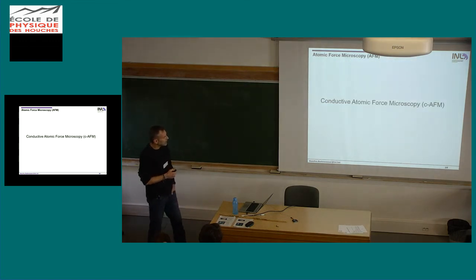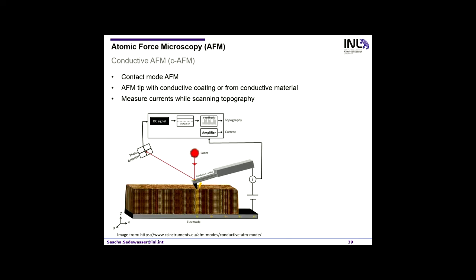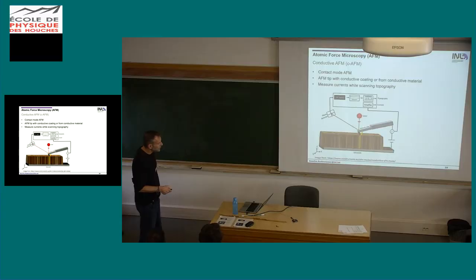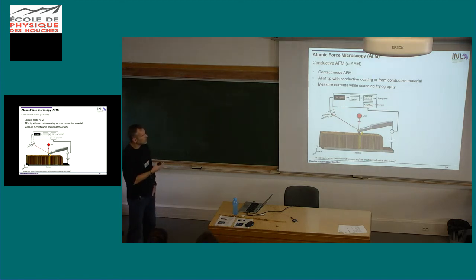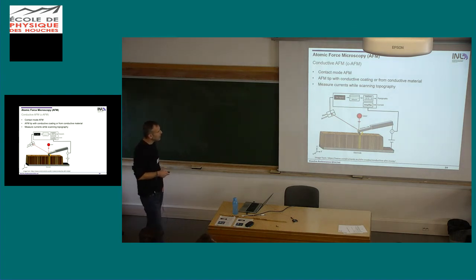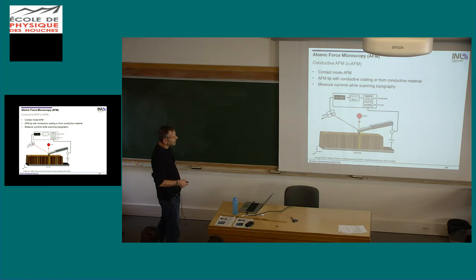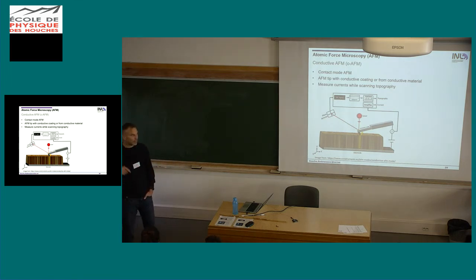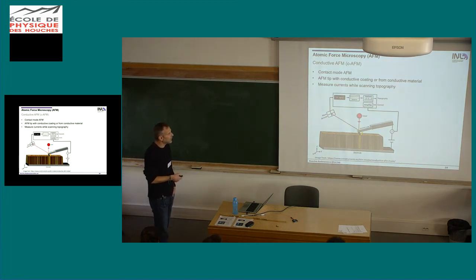The next method is conductive atomic force microscopy. Here what you do is you use a conductive tip and you go again into contact mode, but this time you don't want an oxide here. You don't want an insulator, but you want to measure the current that flows through your sample when you apply a voltage between your tip and the back contact. So this is fairly easy, and most equipment can actually do this. And you just scan the tip across your surface, and you measure, in addition to the topography, as we already saw before, the current. So the only thing you need is a current amplifier in this case.